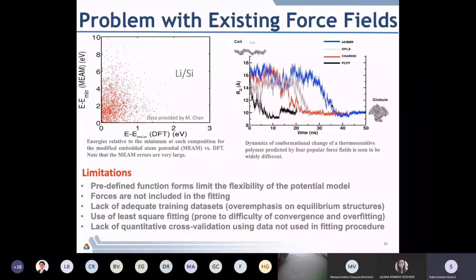So there are some limitations that we have identified, such as the use of predefined functional forms, and forces that are not included in fitting. That is a problem because there is no guarantee that the dynamics you are predicting is correct. Force equals mass times acceleration is essentially what you are doing. And if the forces are not correct and the model is not trained to capture the correct forces, then the dynamics is automatically not going to be correct. That's one aspect. The lack of adequate training data sets with an overemphasis on equilibrium structures is another, and the use of least squares, which is prone to difficulties with convergence and overfitting, and lack of quantitative cross-validation, which is typically not something that is used for developing force fields.